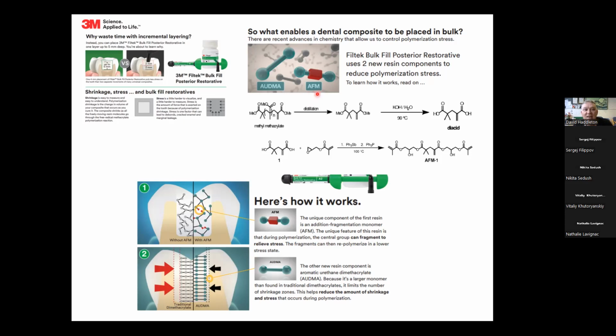You can even get a video, which I haven't got to show you, but they've got this AFM monomer. So the polymerization that takes place in your mouth. Well, actually, I'll do the chemistry first. We do this chemistry ourselves as well. You make a very low molecular weight polymethyl methacrylate oligomer by cobalt. So it's got a hydrogen on the alpha end and this vinyl group on the other end.